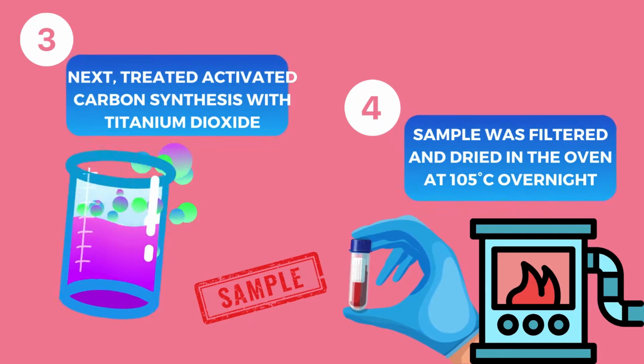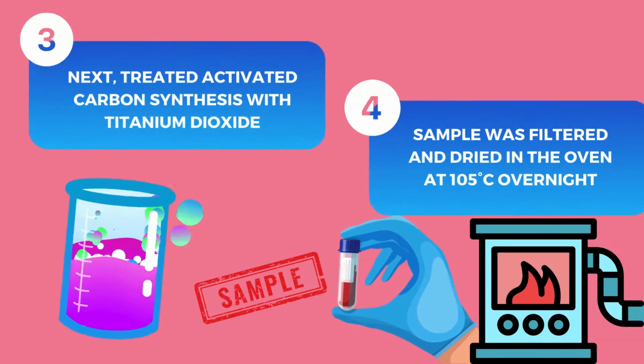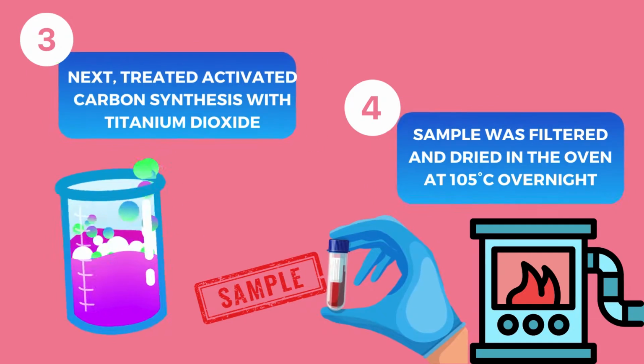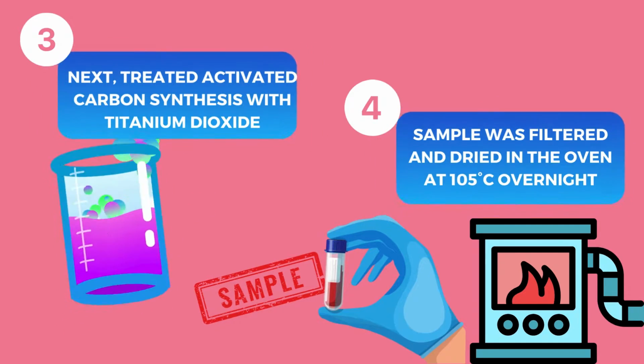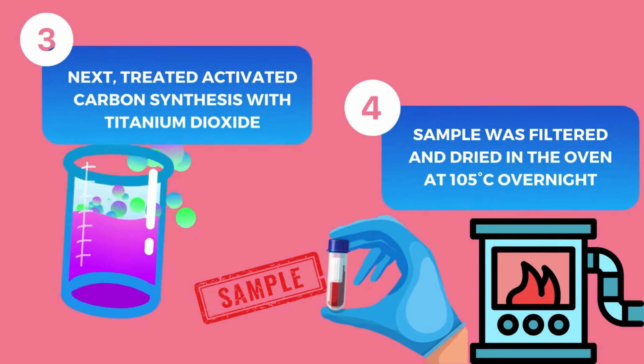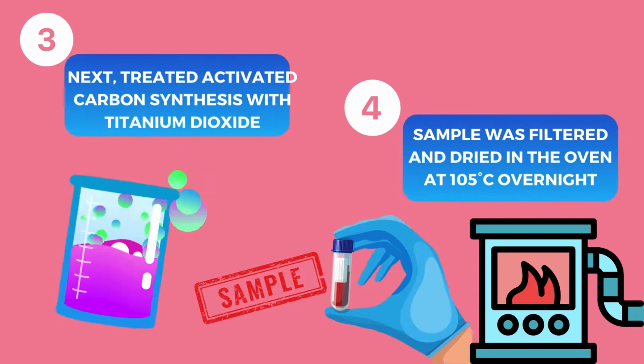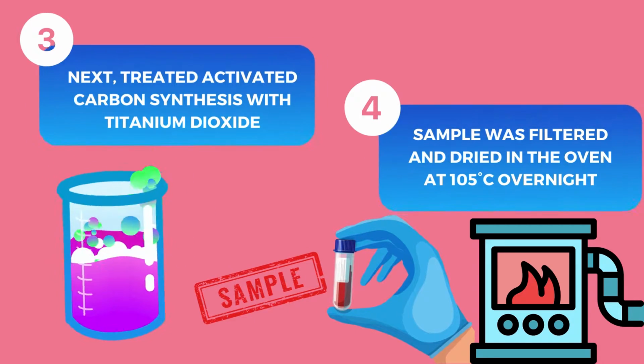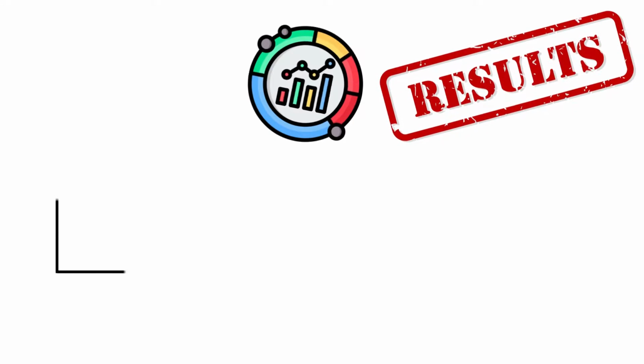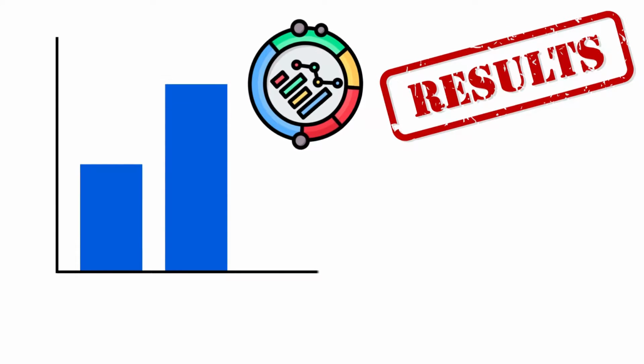Next, in order to produce Titania Activated Carbon Composite, the treated activated carbon was synthesized with titanium dioxide. Then, the sample was filtered and dried in the oven at 105 degrees Celsius overnight. Now, let's move to the result and discussion section.